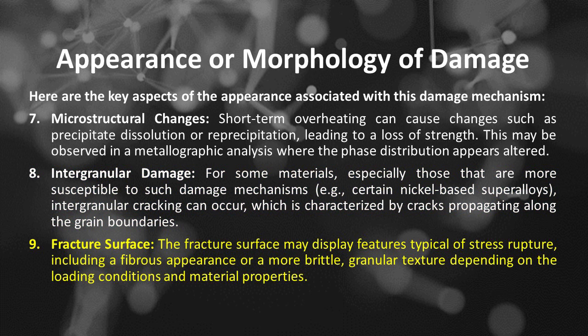Number 9 is fracture surface. The fracture surface may display features typical of stress rupture, including a fibrous appearance or a more brittle, granular texture depending on the loading conditions and material properties.